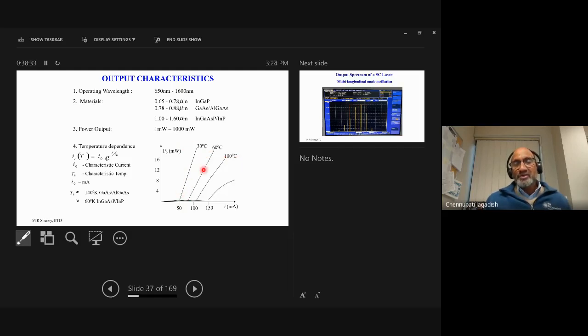If you go to higher temperatures, the threshold current is higher, and as you go to even higher temperatures, the threshold current increases again, and gain saturation also starts taking place because the heat generation pulls down the peak of the gain, which becomes a challenging task. What you want is highly efficient lasers which have very small changes in the threshold current with respect to the temperature, which is really provided by quantum dots, for example. So that's why in recent years people have been focusing on going from quantum wells to quantum nanowires and quantum dots and other things.